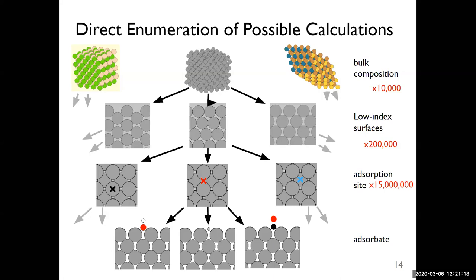And so one way you can do this is you pick a surface and you run some global optimization method like basin hopping as long as you can until you find the absolute best one. The other approach is you consider all the possibilities and make a prediction for all of them, and then find the minimum from those. I am reasonably confident we can do that in terms of where we put something on the surface. I do not know how to do that with the additional degrees of freedom from rotational or swinging things around. If you have any ideas, I am 100% open. That space is just so large. We're still trying to figure that out.